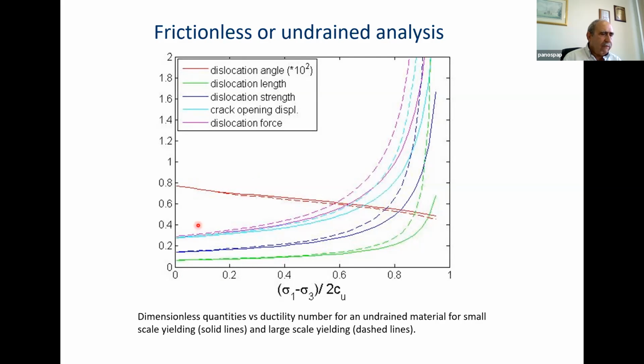We can induce the fracture, it propagates easily. If we are in high stress anisotropy, we are around this area here, which is more difficult to propagate the fracture. We need increasing energy to propagate and induce a fracture.